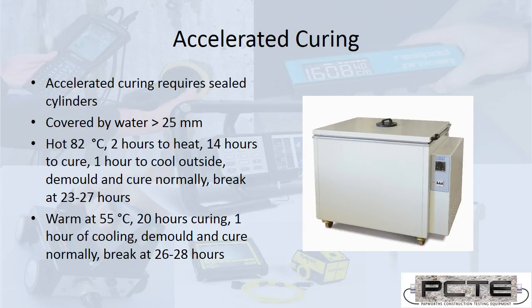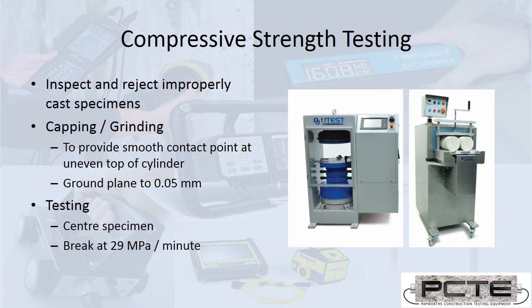The other requirement here is that these are sealed cylinders. These are not just a cover. They actually need to keep the water out to prevent it influencing the concrete inside the mould. So if you're going to be using a match temperature curing system, you need to give some thought, if they're being placed in immediately, to how we are going to protect the unset concrete from the water. And if they're being placed in after a normal setting time, is that water going to be a suitable curing environment? Again, AS 1012.8 defines that it's a lime saturated water environment. So these things need to be considered as part of preparing for the systems. Now, finally, the samples need to be crushed.